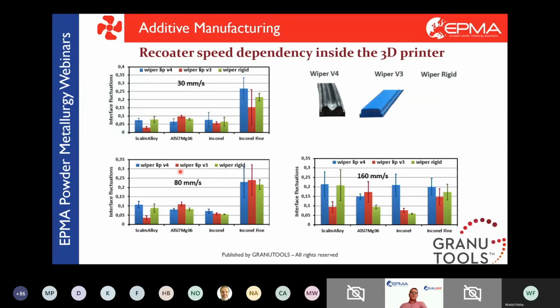For 80 mm per second, we can see that for the 3 powders on the right, we are also in the same range. But for the powder on the left, the Scalmalloy, we start to see a big difference depending on the kind of wiper we are using. However, if you use the double lip one or the rigid one, you get the same interface fluctuation. So this means that powder characterization is still of first importance in that characterization.